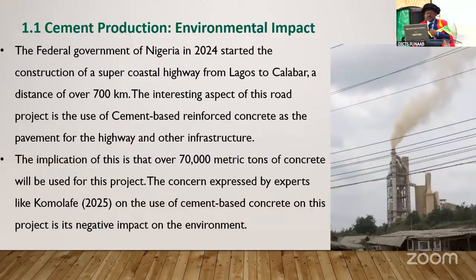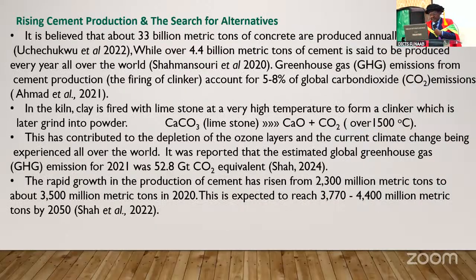Greenhouse gas emission from cement production, that is the firing of clinker, accounts for between 5 to 8% of global carbon dioxide emissions, according to Ahmad et al., 2021. In the kiln, clay is fired with limestone at a very high temperature to form a clinker, which is later ground into powder. The limestone equation, CaCO3, when fired, gives us calcium oxide, which is used for cement, and the carbon dioxide is released to the atmosphere. This has contributed to the depletion of the ozone layer and the current climate change being experienced all over the world.